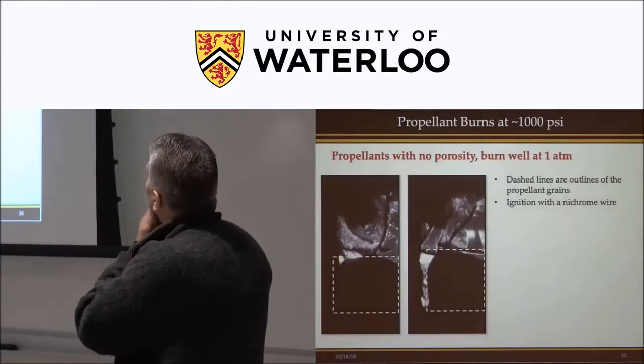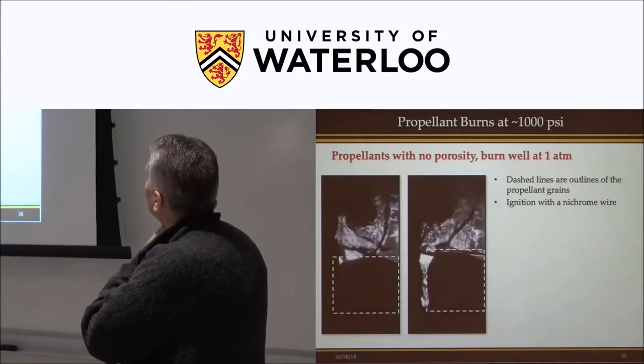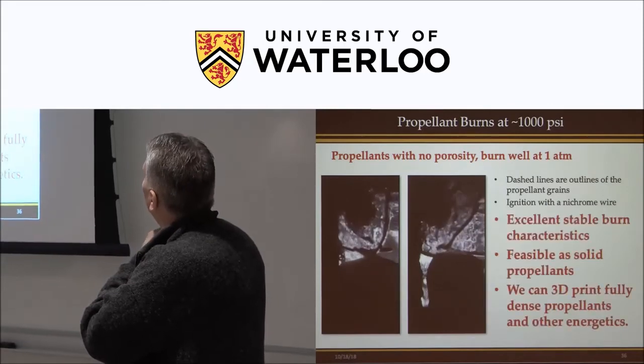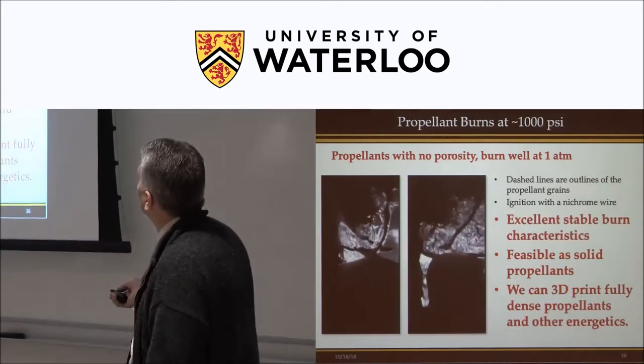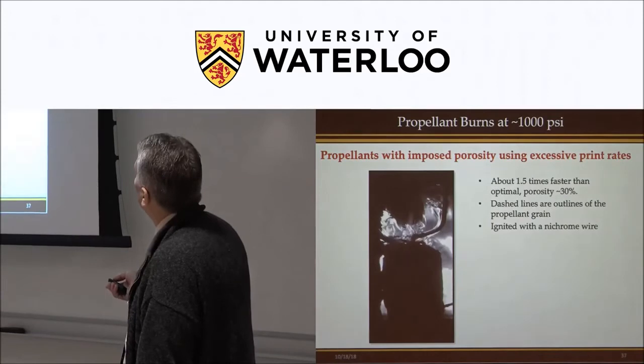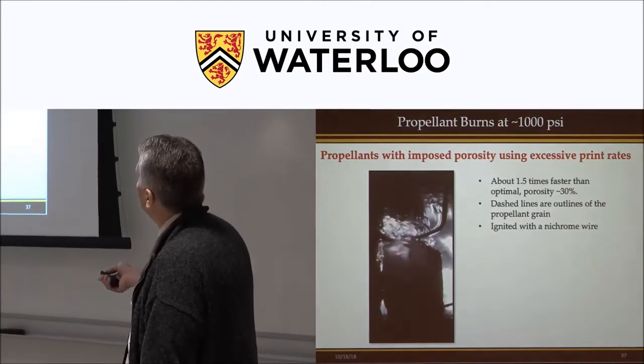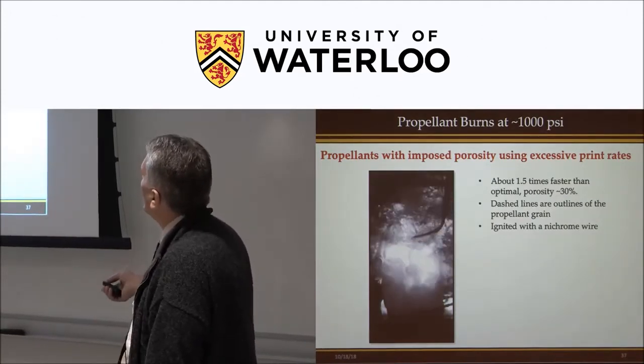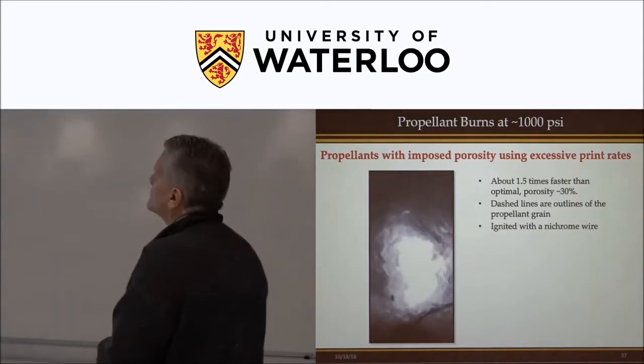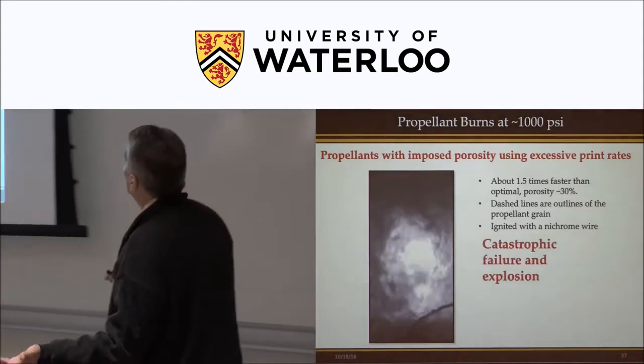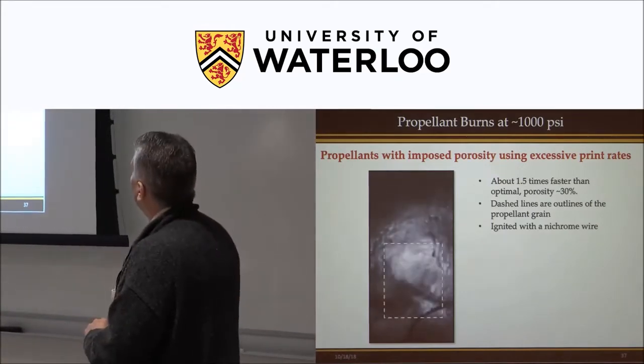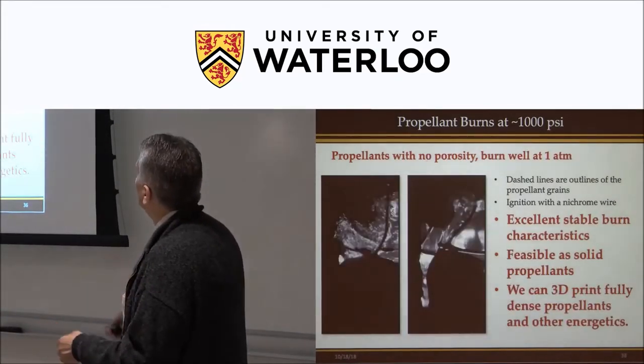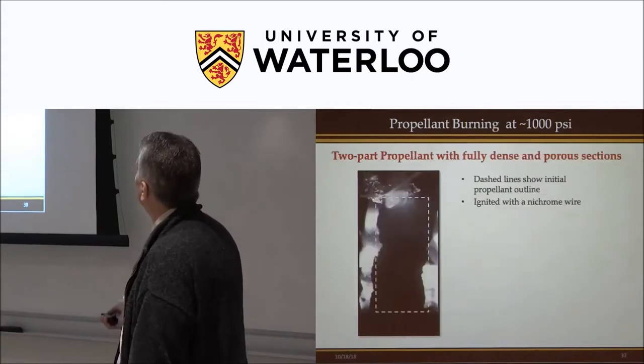So this is burned at one atmosphere. One atmosphere is relatively easy to work with. But importantly, at pressure it burns well. If we add porosity, though, we can make that strand explode. So we can introduce porosity if we want, or have cases that, even at pressure, burn in a normal fashion as you would like.